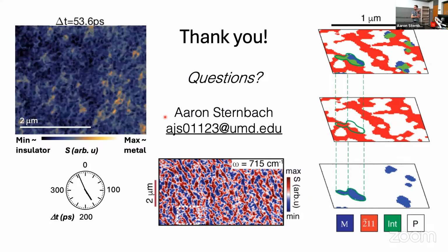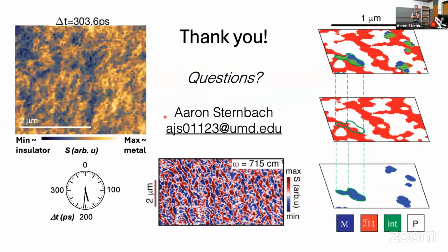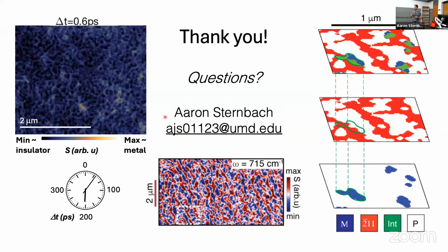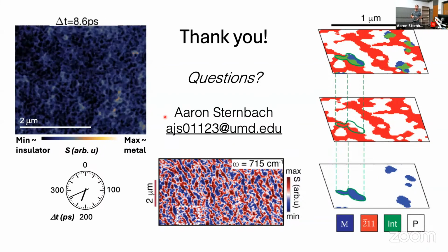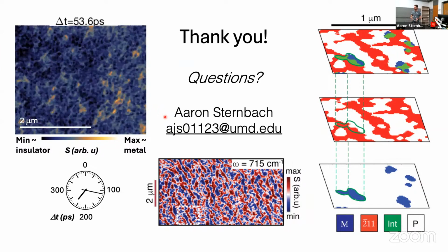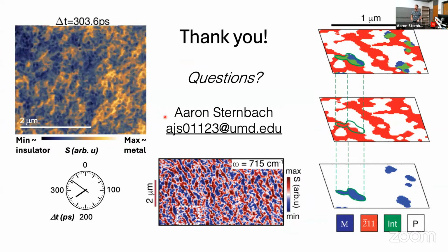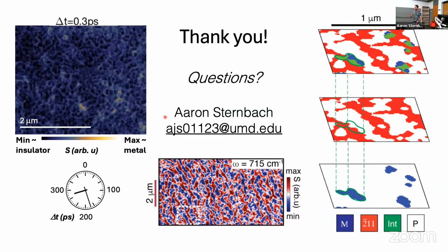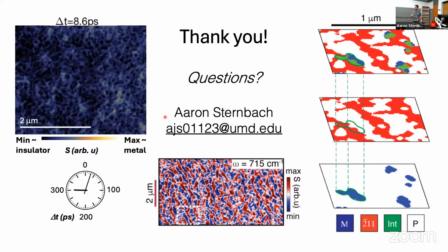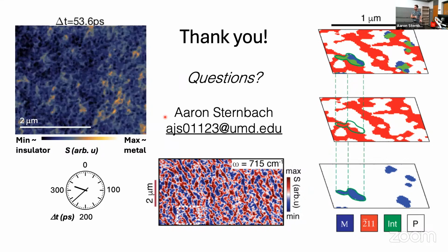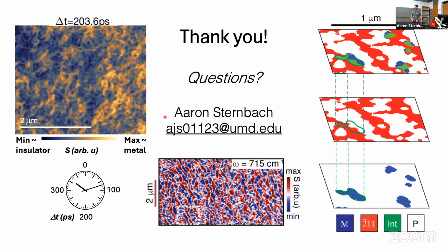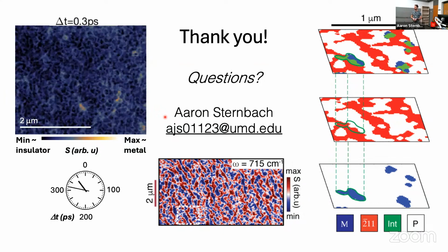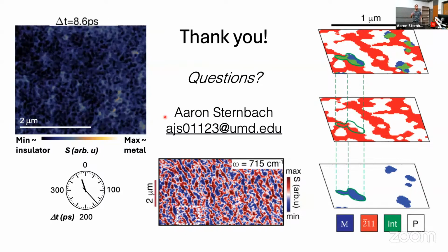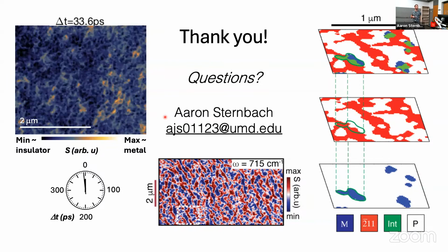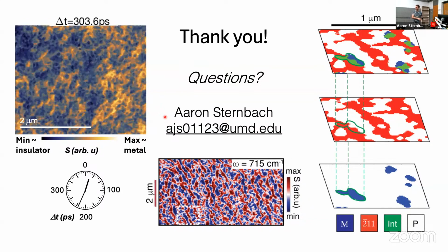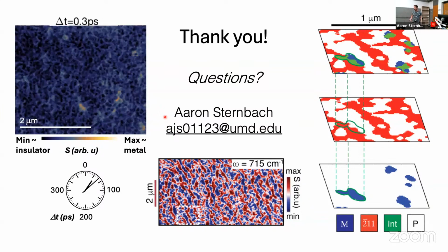From the question of the fundamental physics of this system, the electronic transition could be associated with a Mott transition. So the system is a Mott insulator. The structural transition, however, comes with a unit cell doubling and a Peierls distortion that opens a band gap in the system. And so whether that gives rise to the insulating behavior or if it's the electronic correlations is sort of the open question. Now, evidence is increasingly pointing to this being what's called a Peierls assisted Mott transition, meaning both of these things are playing a role.